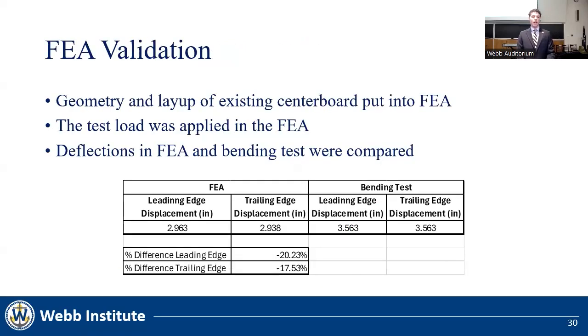After setting up the finite element model, we could validate it using the data from the existing centerboards. We recreated the geometry and the layup of the existing centerboards in our FEA model and applied the same load in the FEA as in the bending test. The deflections from the FEA and the bending test were compared. In the SOLIDWORKS model, the leading edge and trailing edge displacements were both just under 3 inches, while in the bending test, they were both just over 3.5 inches.